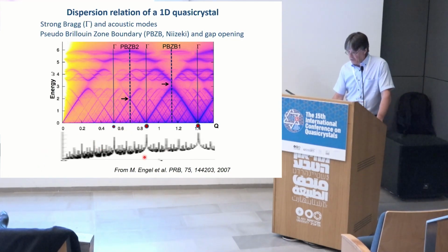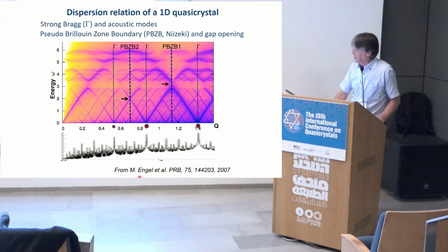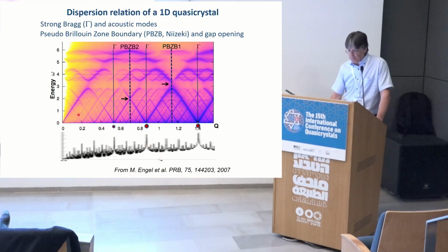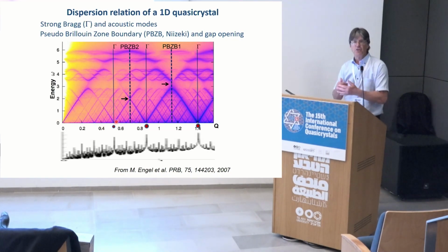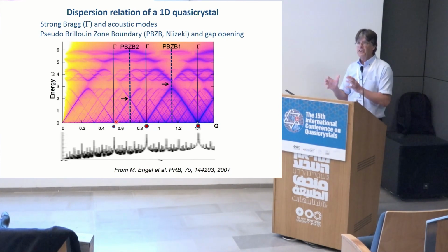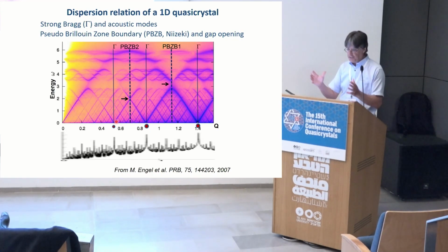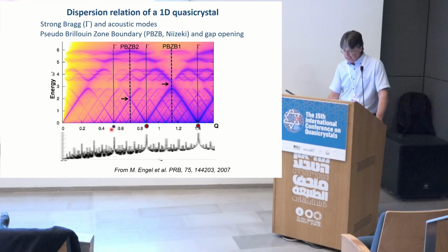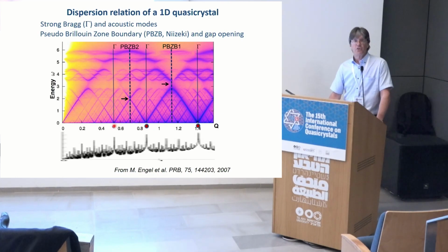this is a picture taken from the work of Michael Engel. Sorry, something went wrong here with the diffraction pattern, but it's the same as for electrons. Because this is a one-dimensional quasicrystal, because we have long-range order and no periodicity, there is a range for which the states are so-called critical. But the main point I want to make here is that although we cannot define a zone boundary because we don't have periodicity, we can define pseudo-zone boundaries which are related to strong Bragg peaks, strong Bragg components.